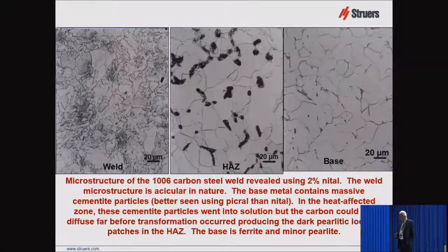And here are higher mag views of 500X. This is the weld metal, the heat affected zone. You can see the perlite patches are degenerate perlite because the perlite started going into solution, then on cooling, it precipitates out, and it's no longer lamellar. And in the base metal here, you can see we have a little bit of perlite. They're very small patches. We got inclusions in here too.